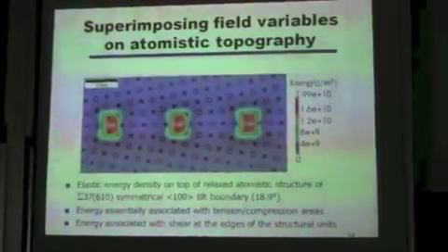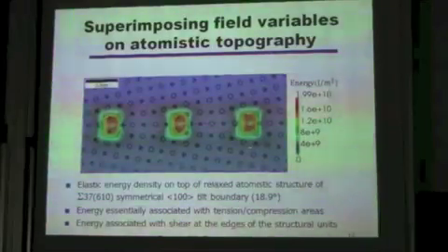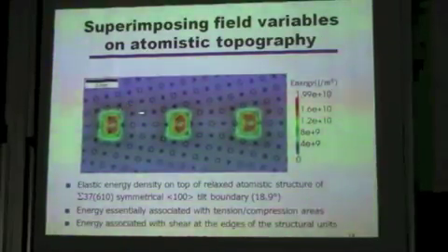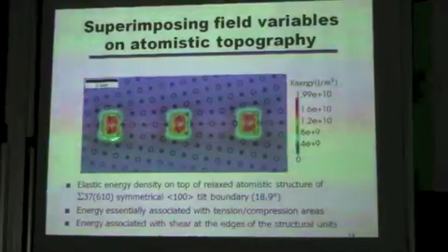So you notice that the elastic energy is evenly distributed along the grain boundary. It is mainly due to tension/compression. There is a small amount of energy around this which is due to shear, but mainly it's due to tension/compression along the dipoles. Note also again the scale, so that means that the width of the grain boundary is about 0.5 nanometers.